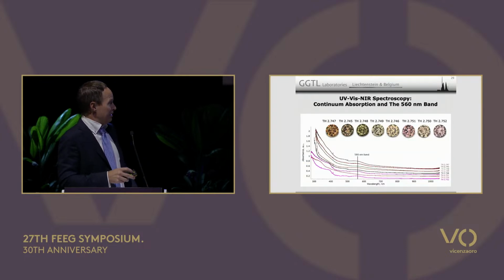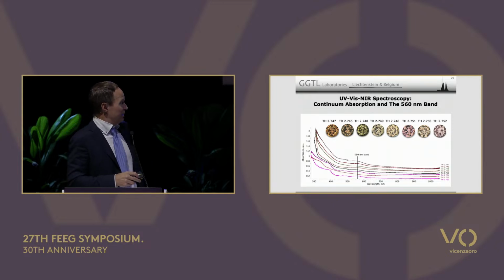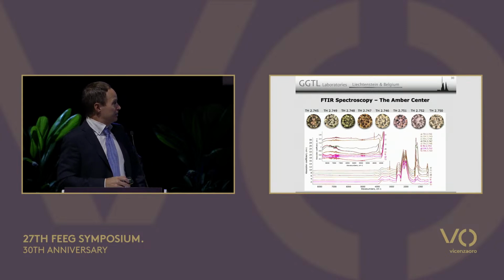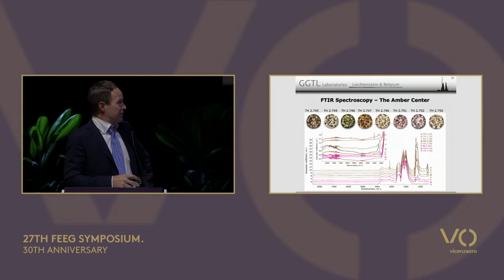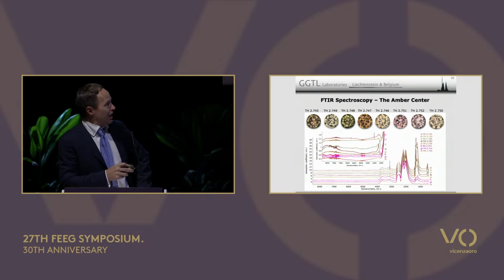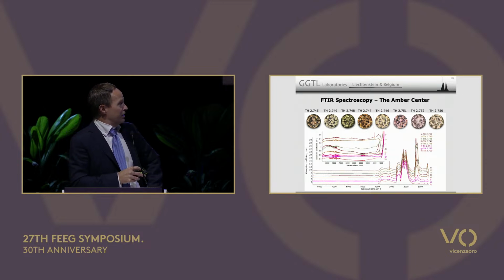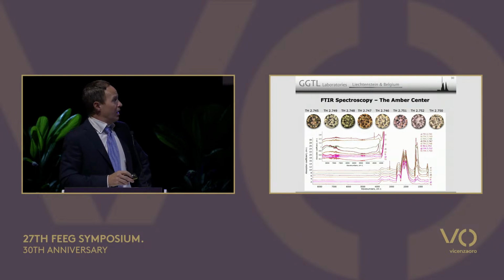The samples we have, they have the typical spectroscopy, nothing too unusual here. Infrared spectroscopy, nothing too unusual either, exactly what we expected. The browns have an amber center, the olives as well, and the pinks do not. So pink down here, the amber center is practically absent, which is the typical and expected result. And also down here, the pink is very low in nitrogen. This stone is actually a type 2A, and the browns and olives are higher in nitrogen.